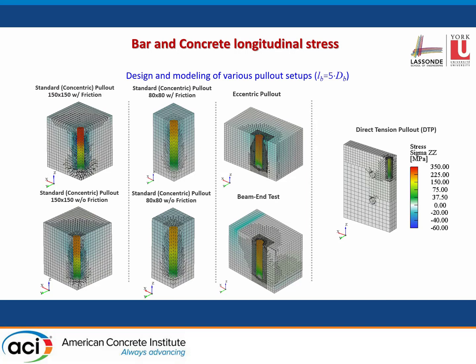And the color code is the same throughout. So where you see red in the bars, that represents the stress level that was developed in the bar. So you see, for instance, in the standard pullout, you could reach 350 megapascal stress in the steel bar for 5 Db development. Whereas in a direct tension pullout, the development capacity of the bar would not exceed 75 megapascals for the same anchorage length.